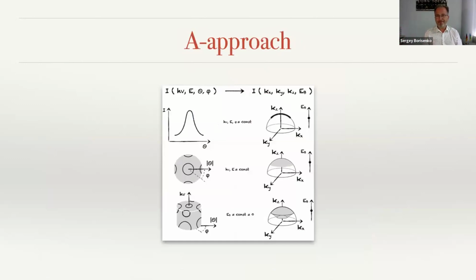What to do? The A approach. A stays in ARPES for angle, and the A approach is trivial. One considers angle first of all. If we consider this curve, it is a momentum distribution curve. It is an angular distribution curve, but translated to momentum like a momentum distribution curve. And it has a very transparent physical meaning. It is indeed the intensity distribution in K-space sitting on this emission sphere.